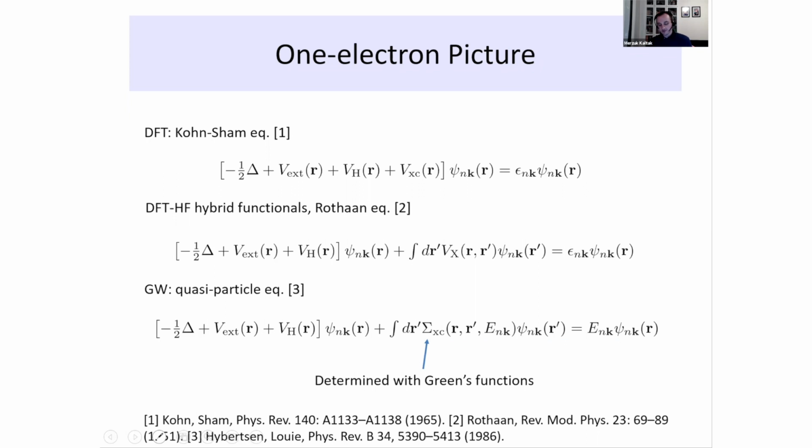These files correspond to the screening of the Kohn-Sham wave functions. After you've done one loop in the GW, you will get a new WAVECAR. If you restart the GW step from this WAVECAR, you will actually recompute the screening. That's different from a self-consistent scheme where you freeze the screening.